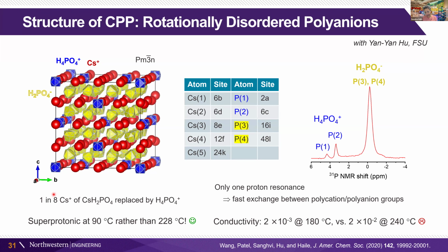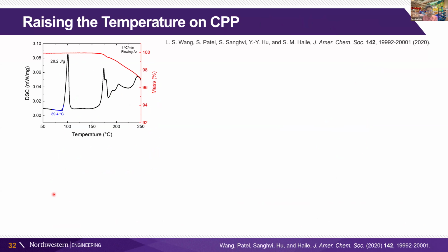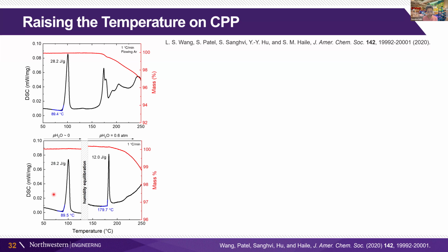Unfortunately, the conductivity is an order of magnitude lower than that of the cesium dihydrogen phosphate. Maybe not so surprising because the temperature at which we measured this compound is a little bit lower. Then we increased the temperature on this material, seeing what its dehydration behavior is. So we see a dehydration result. But what we also saw when we increased the steam partial pressure is that it has another phase transition.